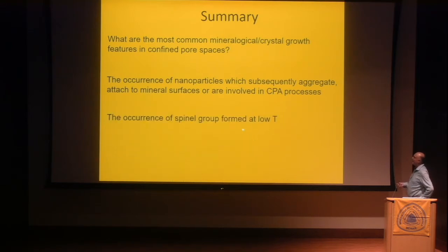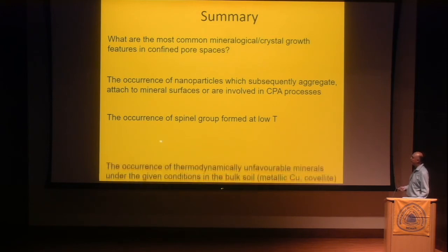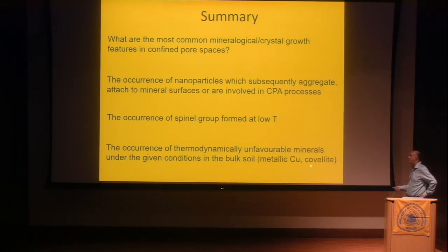We see a lot of spinel group minerals formed at low temperature. That was really a surprising feature, and we still haven't really understood how and why they form. Normally you would expect that they form in high temperature processes, but we see them all as nanophases within those confined pore spaces. And obviously, because we are in confined pore spaces, we see a lot of minerals that are thermodynamically unfavorable, considering that we only collected soils in the upper 5 centimeters. So we find metallic copper and covellite in the top 5 centimeters of a soil. They're not supposed to be there. Or we find jarosite, a very acidic iron sulfate, in soils that are at near-neutral pH conditions. So there are many minerals that we do not expect.